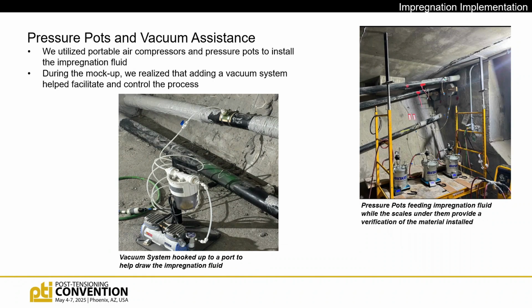And then this is a picture here of the pressure pot setup. So this was a good way to make sure we had some quality control on what we were putting in, but we'd pressurize the impregnation fluid, put it in these pressure pots, and then we weigh the pots as well. So we had both: we lost this volume of fluid, we were able to track the buckets, but we also knew it by weight. And then on the other side, you can see the vacuum assisting where we were pulling it as well, which helped to make sure that we put the impregnation fluid where it was supposed to go and not throughout. And I believe it's back to you after this.